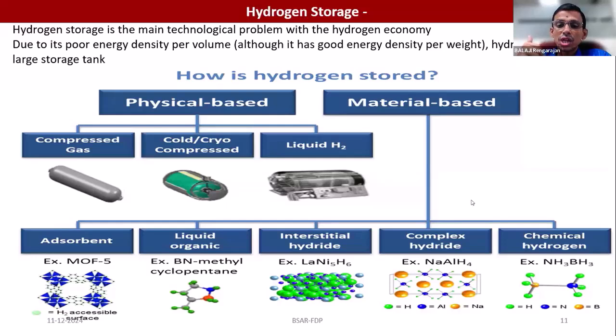But the compression of hydrogen to elevated pressure is also tricky, because when you store the compressed gas in sealed cylinders at more than 150 bar, the hydrogen has the tendency to cause embrittlement. In metal cylinders at elevated pressure, the metal embrittlement will happen, which leads to explosion of the cylinders. So it is not recommended to store hydrogen at more than 150 bar in steel cylinders. We have to look at an alternative method of storing hydrogen at elevated pressure.